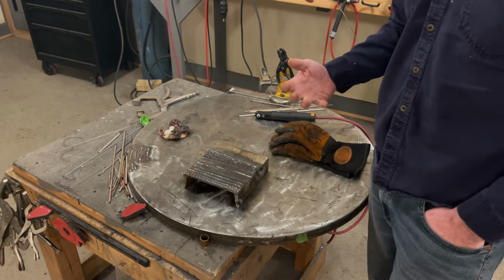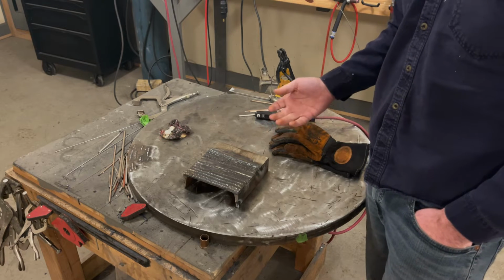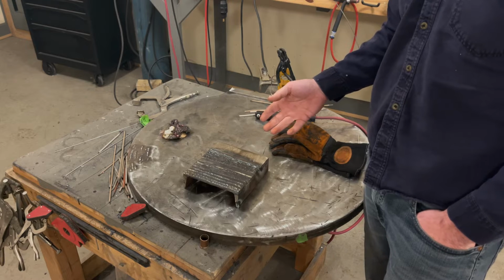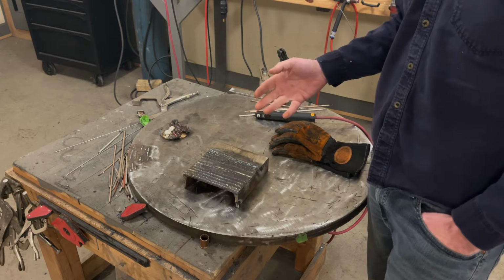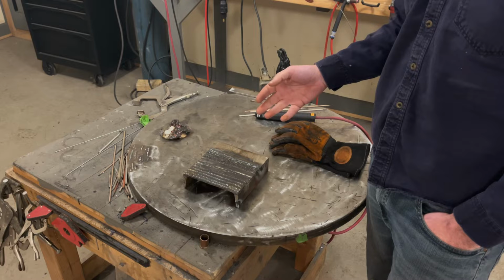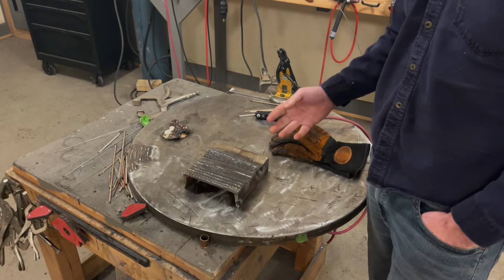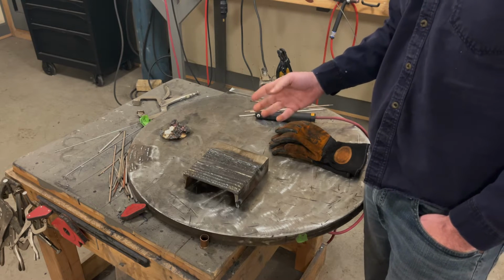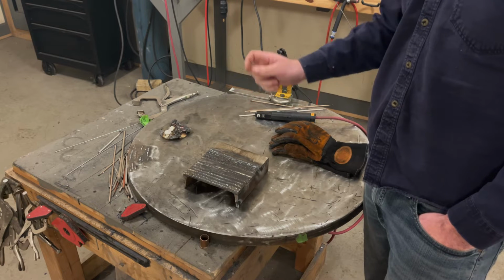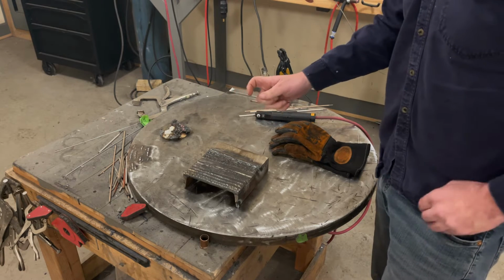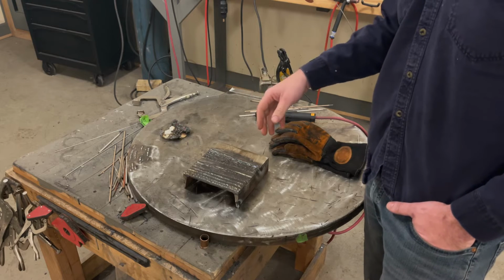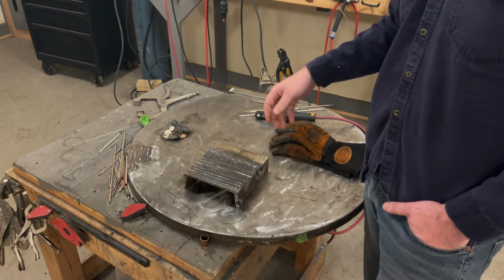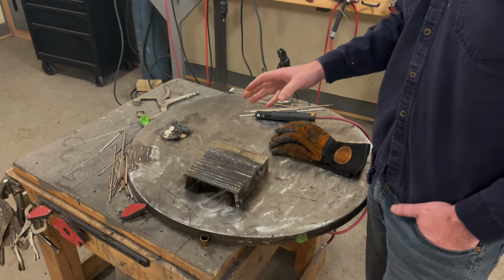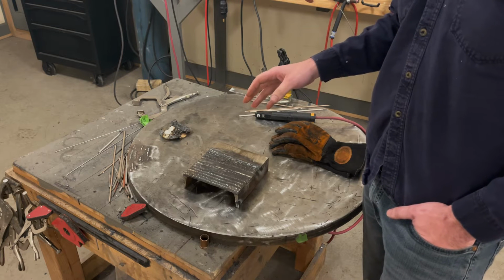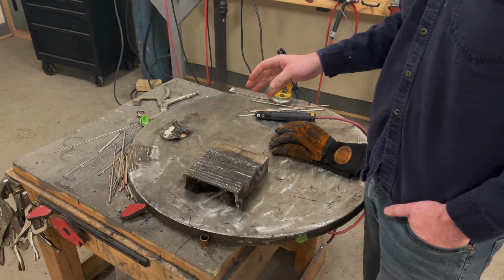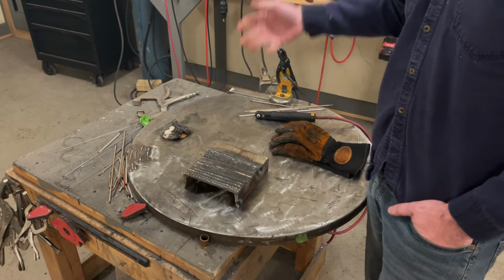Now, from a personal perspective, I do not like running 6013 uphill. I find that it just doesn't deposit enough metal and you have to cram the rod into the puddle. And if you don't do that, your arc gap gets too long and you essentially just start undercutting your metal, and too much heat and the molten metal just drips off. Across the board, it's pretty difficult to run uphill, but that doesn't mean it's impossible. So that's what we're going to be working on. Let's get into it.